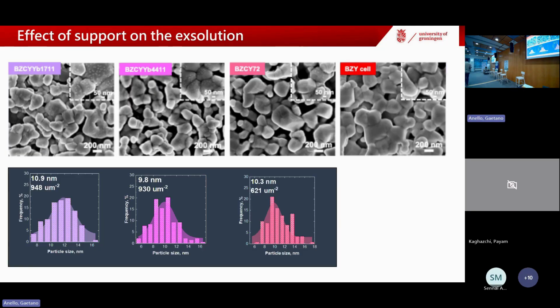So this actually shows, and it's something that is not often reported, that the selection of the ceramic electrolyte for your process could be detrimental also for the performance of your electrode, not only about the conductivity that you want to have. So we should take it into important consideration, particularly with the material that we are handling in this case.